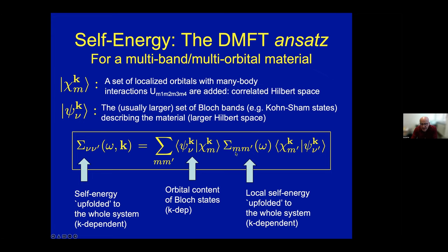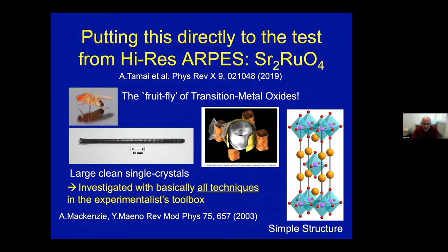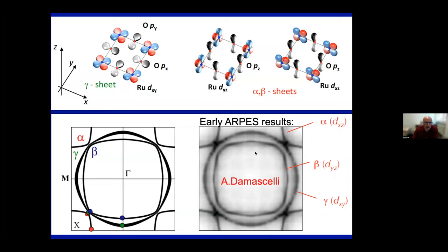Hence, the accurate statement is that when expressed in the basis of local orbitals, the DMFT ansatz is that the self-energy is momentum independent. But then when unfolded to the whole solid, it acquires momentum dependence. And this can be applied, for example, to materials like strontium ruthenate, Sr2RuO4, which is an oxide involving 4 electrons in the ruthenium d shell. This oxide has a very simple electronic structure because these electrons live in a subshell of 3 levels among the 5 d orbitals, which is called the t2g